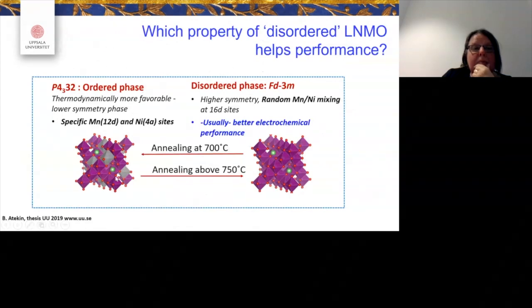And this compound you can find in an ordered phase or in a disordered phase. And you get the ordered one if you anneal your synthesis below 700, and the disordered one if you anneal it above 750. And this ordered phase is then thermodynamically more stable. You have very specific manganese and nickel sites. And here you have a random mixing of manganese and nickel in this one. And the interesting thing is when you put it into a battery and you charge it, it's this disordered phase which gives you much better electrochemical performance. So why?